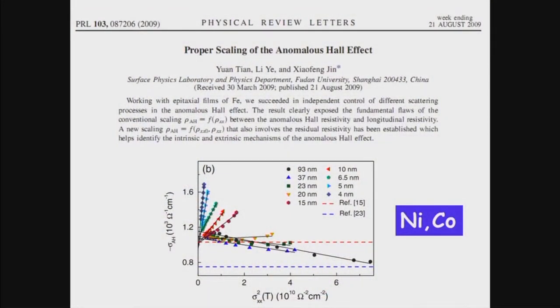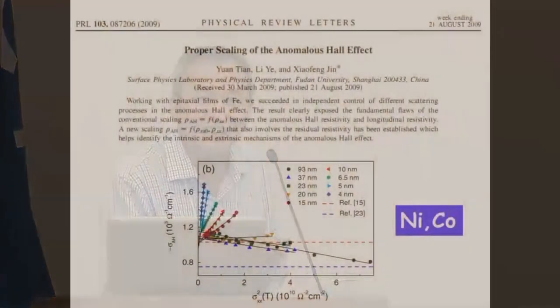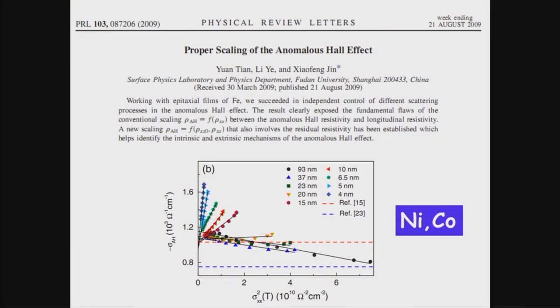When we published this paper, we did it with iron, but later on we also checked with nickel and cobalt, and did the same thing. With all our modern facility, we basically just reproduce the result Edwin Hall did 130 years ago. So this cobalt has an intercept around here, but it's positive. But the nickel is indeed negative at the backside. So that was a very interesting observation. Nowadays, with ab initio calculation, you can confirm this is just a pure electronic band structure result. Any graduate student can confirm that cobalt and iron have Berry curvature positive, and nickel has a negative.